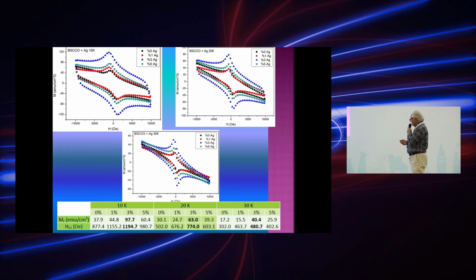Later on, we have measured magnetic hysteresis of all samples for different temperature intervals. You can see that by increasing the silver amount, the area of the loop is increasing. The pristine sample has a very lower area in comparison to the silver addition. And by increasing temperature, you can see here the area of the loop is getting lower.